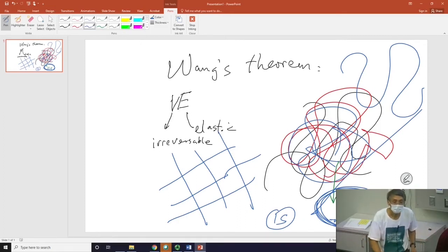You have a viscoelastic material where the elastic structure, may I use the word, survives for a certain period of time. In this case, it's about 10 seconds. Survives. So anything within that time frame, the material is elastic because that structure survives. Beyond which, it falls apart. And that's why we have a viscous component in there. So,